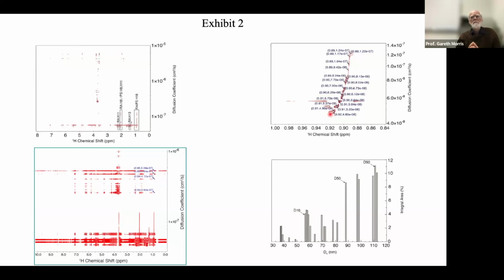Now, so far, I haven't really talked about the actual diffusion coefficients, except to say that big things diffuse slowly and small things diffuse rapidly. But I did say that doing really accurate diffusion measurements could be really difficult. That's maybe a little bit too gloomy. Getting a diffusion coefficient to within a couple of percent is well within the range of standard instrumentation and standard methods. But how can we interpret it?